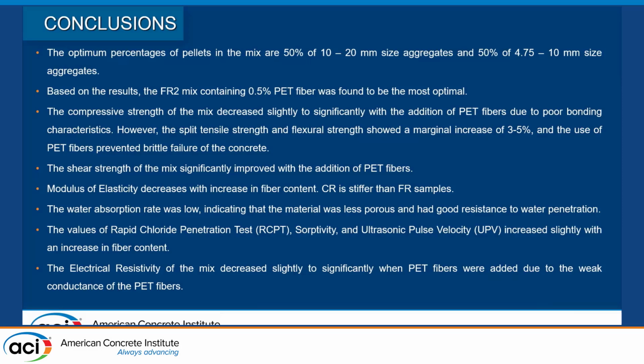Coming to the conclusions, the 50-50% introduction of coarse aggregate was found to be the optimum one, and fiber reinforcement with 0.5% PET fibers was found to be the most optimal specimen. If we talk about compressive strength, there was a slight reduction with the introduction of fibers, but we can say that was due to improper bonding. We found that the shear strength increased, and the other durability parameters like the RCPT test, sorptivity, and UPV test increased with increase in the fiber content, which is a good thing. And lastly, the electrical resistivity also decreased with the introduction of PET fibers, and that's it.